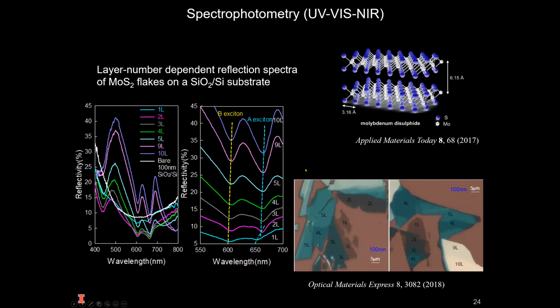This is a study where optical properties of molybdenum disulfide flakes were studied as a function of the number of layers. The A and B excitons in this figure arise from direct band gap transitions at the K point, due to a spin orbit split valence band and the degenerate conduction band at that point.